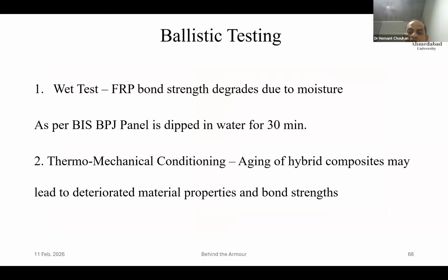So you have to make sure that because of moisture your panel is not damaged. Different standards have different times. We provide a sealing to this panel, and then this panel has to be dipped inside a water tank at least more than 100 or 150 millimeters. So there is a water head requirement. In case your pouch is punctured or your material is affected by moisture or water, it will serve as a lubricant and your bullet will perforate like anything. If this is made out of Kevlar and you touched water to the Kevlar, there is no need to test the panel. It's bound to fail.